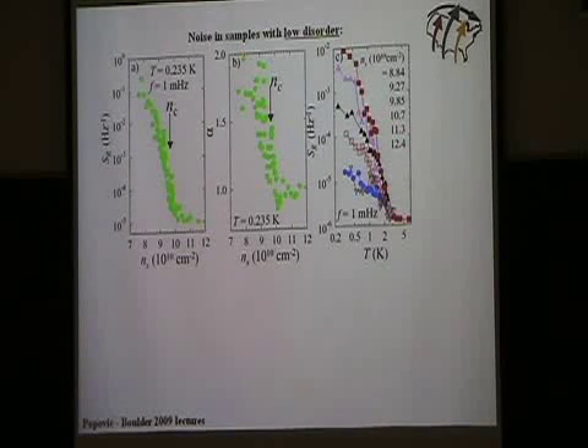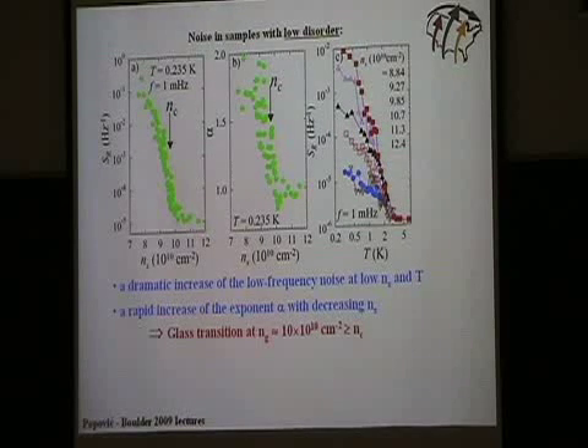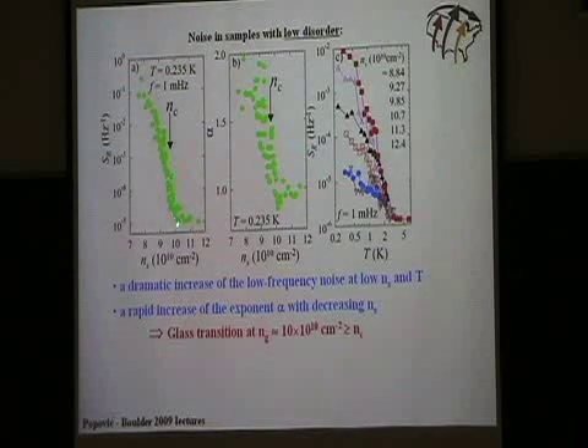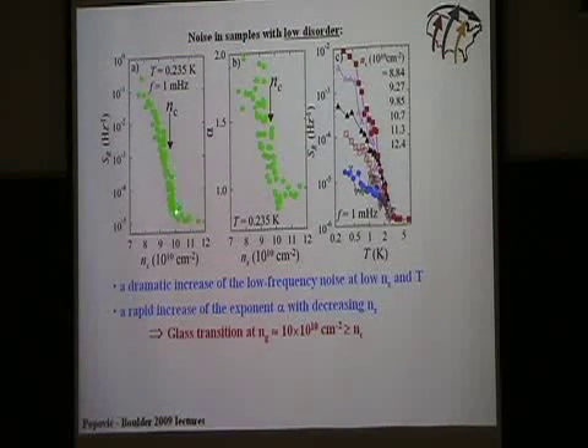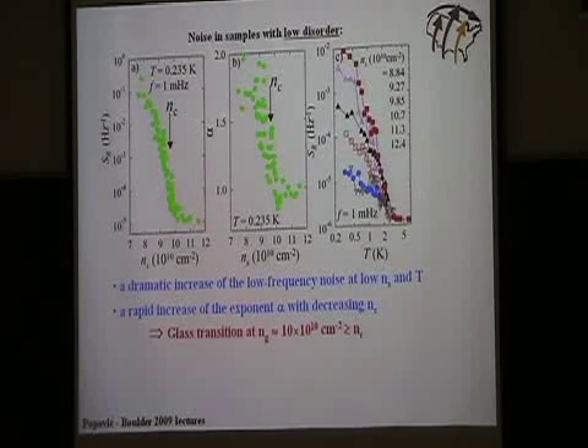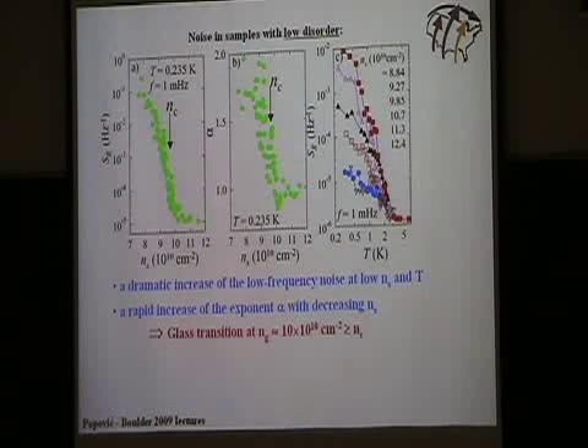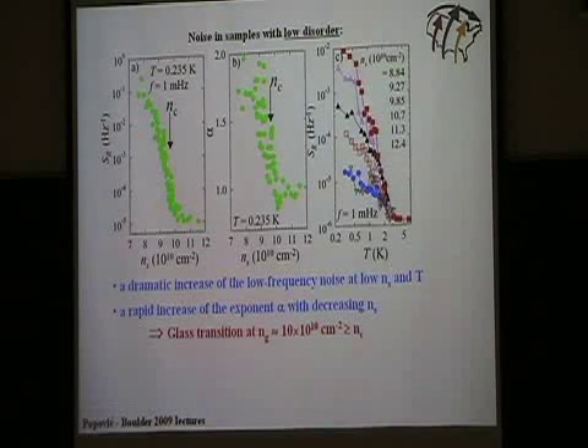So if we use these noise results, we can identify again the glass transition, and we find that in these samples the glass transition is very close to or just slightly above the critical density for the metal-insulator transition. This is what I was saying yesterday, that in these samples with low disorder, this intermediate metallic glassy phase essentially disappears. The metal-insulator transition and the glass transition more or less coincide.